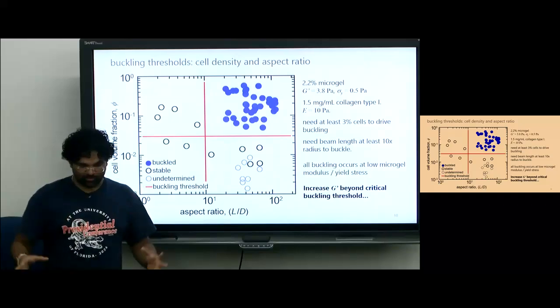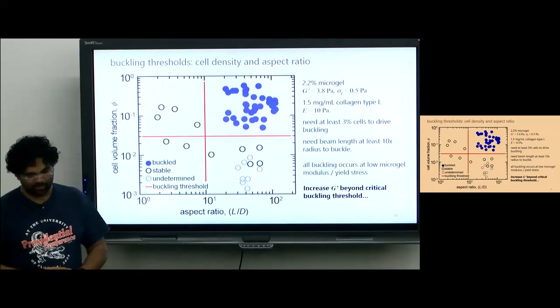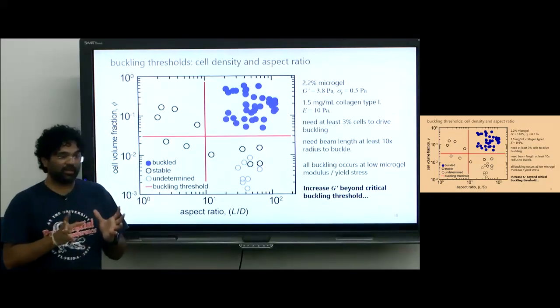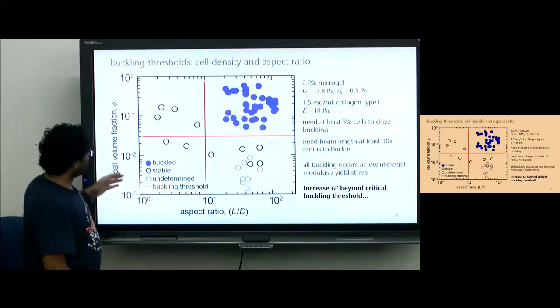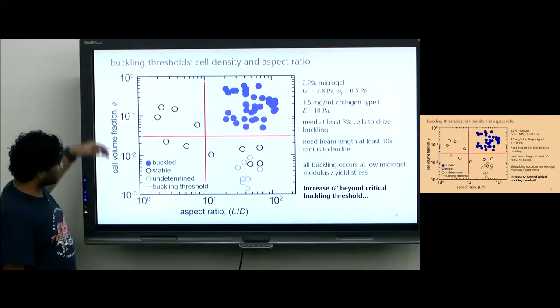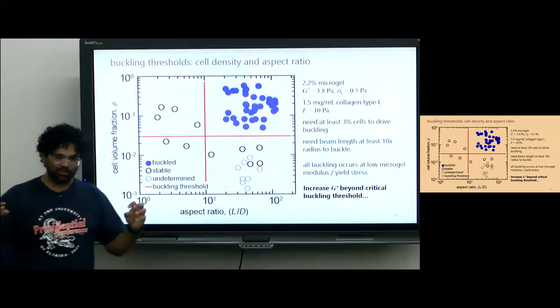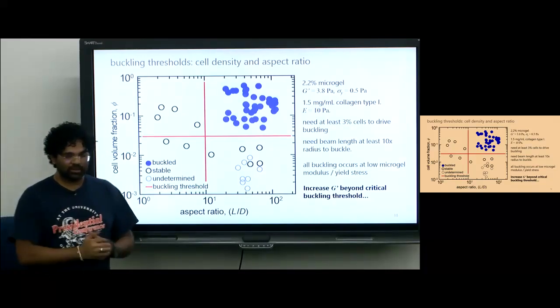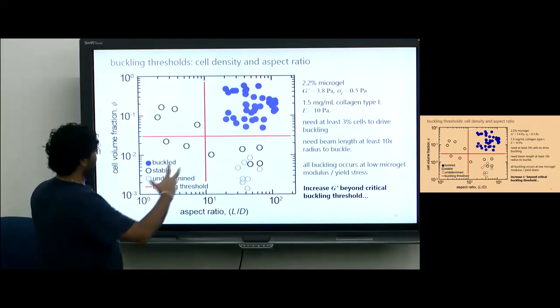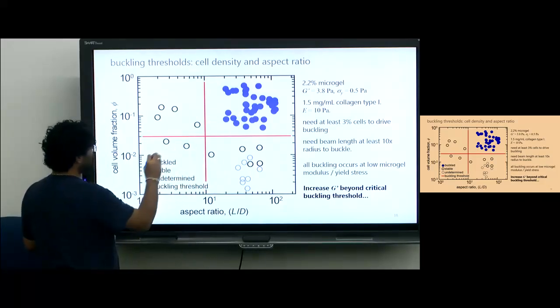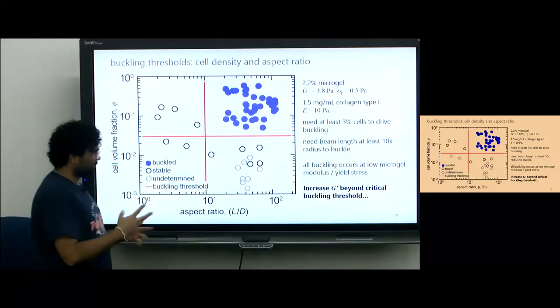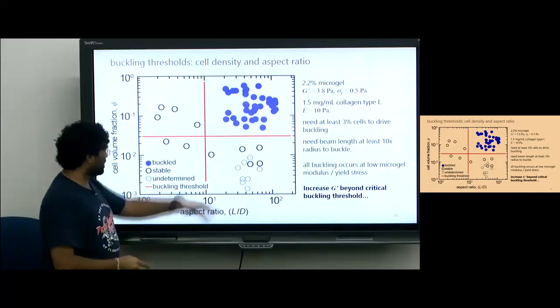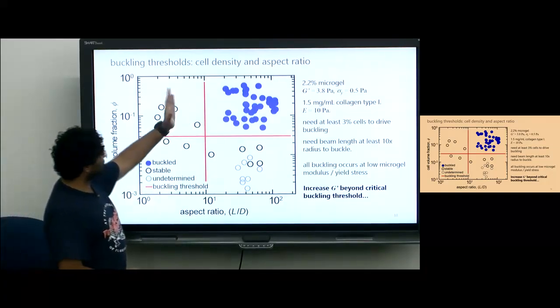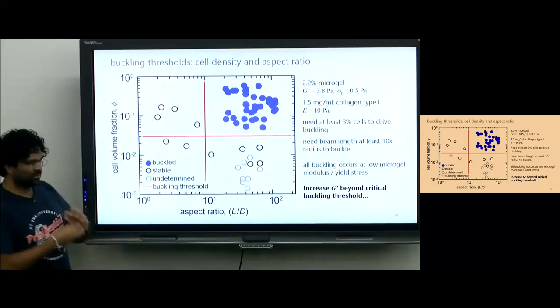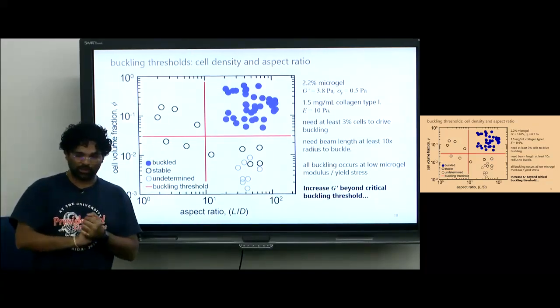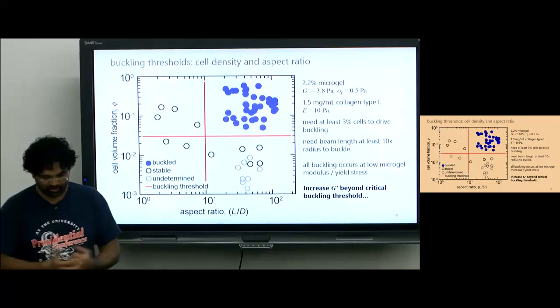From here, they mapped out this buckling behavior in a phase diagram. What if we increase the number of cells versus increasing the aspect ratio of the beams, and how does that affect the behavior, right? We can characterize it as buckled beams or stable beams. In some cases it was not possible to determine it, so it was undetermined. And then we can figure out what threshold volume fraction and aspect ratio you need so that you get stable structures instead of buckling structures.